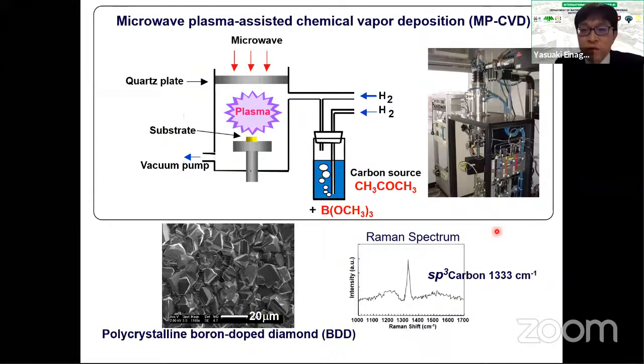So how do we make diamond? This is our microwave plasma-assisted CVD machine in our lab. It is very simple. We use acetone as the carbon source and trimethyl borate as the boron source. These are a liquid carbon source and a liquid boron source, just mixed. By controlling the concentration, we can control the conductivity from insulator to metal-like conductivity. By using this CVD method, we can make boron-doped diamond on the substrate. This is an SEM image of the polycrystalline boron-doped diamond. This shows the conductivity.